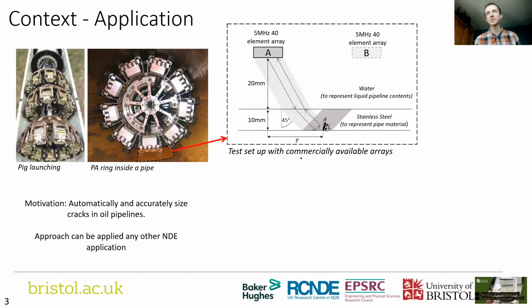I don't have access to one of these, so I've got a test setup that's trying to replicate it, and that's water rather than oil. And I've got my arrays that fire plane waves that travel through the water into a stainless steel plate, and that bounces off defects. So I'm just looking at cracks on the far surface wall, and the sound bounces back off and back to the array.